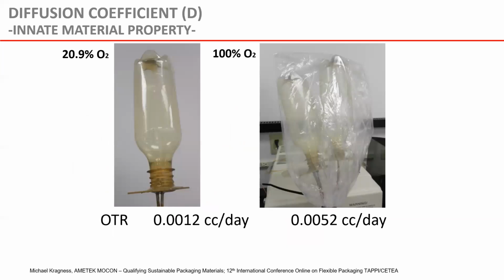Now, to talk a little bit more in depth about the diffusion coefficient, it's an innate material property. For each type of polymer or each type of material, it will have its own diffusion coefficient that correlates to some chemical species. In this example, that chemical species is oxygen. So we're testing a bottle at room air concentration, 20.9% oxygen, and at 100% oxygen, where we bagged the bottles and piped in 100% oxygen. So we're going to challenge those with 100% oxygen.